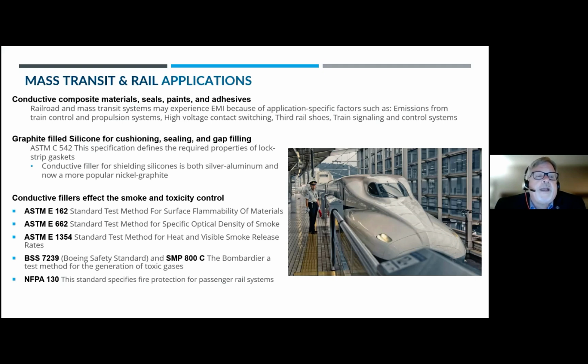ASTM standard C542 defines the required properties for these gaskets. The conductive fillers for shielding silicones are typically silver aluminum, but more and more it's starting to be nickel graphite, mostly due to the cost of the silver aluminum fillers. So those are some of the fillers that are being used to help provide conductivity in the composites, whether thermoplastic or thermoset materials. And of course, nickel graphite and silver aluminum are metal and expensive and have some weight to them.